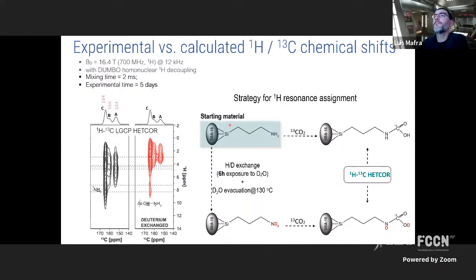We have tried other approaches where, prior to CO2 absorption, we exchange all the labile protons with heavy water. And then instead of protons, we have the deuterium now. And then after that, we just reabsorb with CO2. And hopefully we see that these protons will disappear from the spectrum. You can see some peaks disappear, which can help us. We have done this systematically for all amines. I will not show you all the amines, of course, but this greatly helped us to really have an unambiguous assignment of certain protons, at least, certain proton environments.